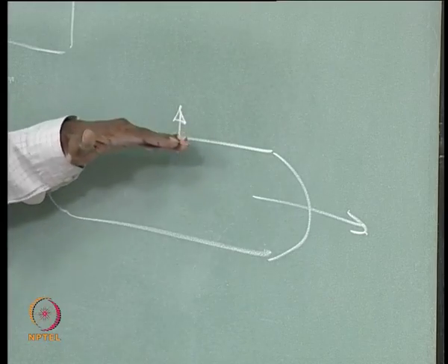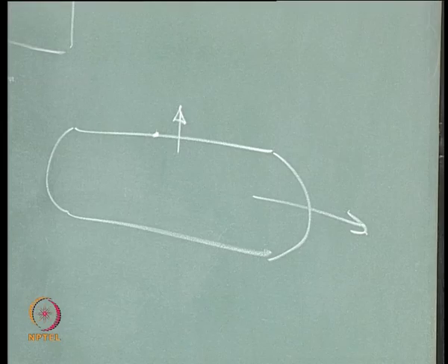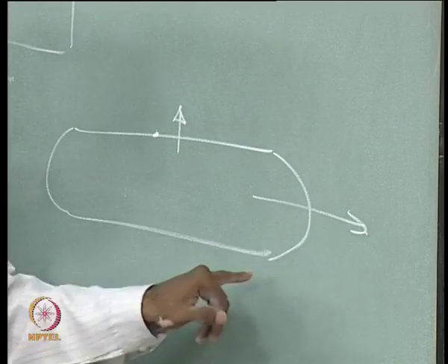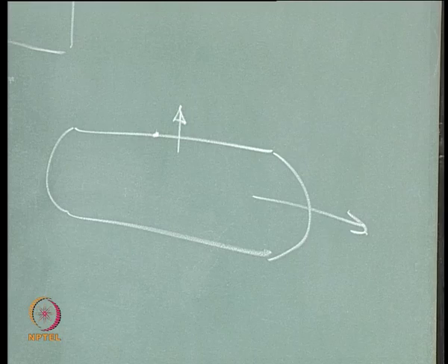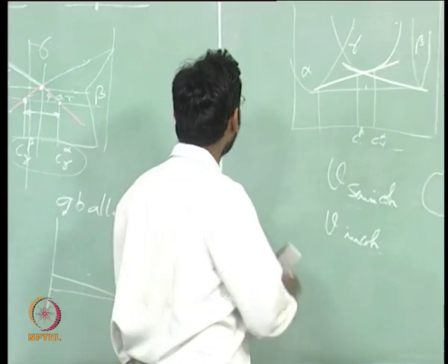This growth is much faster than this growth, because if you want this growth to occur, then you need to maintain the coherency continuously. The continuity of the atomic planes has to be maintained, whereas here there is no need of such a thing. So as a result, you see that at higher temperatures, if you take the ratio of,